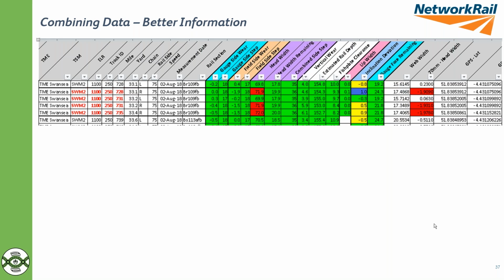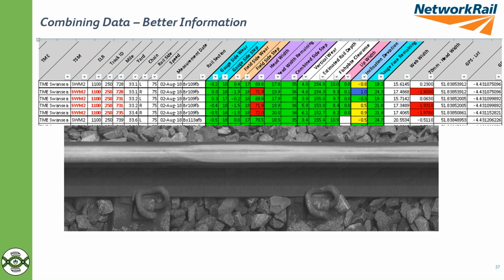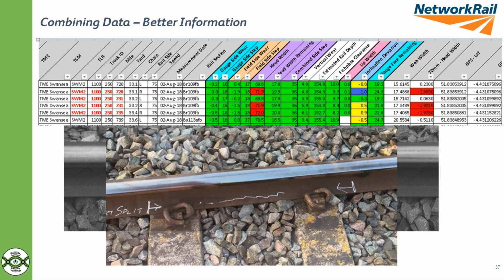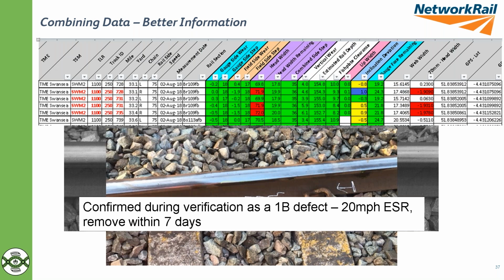It then got picked up by a UTU, and independently, a suspect was indicated from the UTU of a possible vertical longitudinal split. That is an image of it from the PLPR that we can see. You see the widening locally at that point. And when we got the ultrasonics out to confirm it, they were able to mark up the extent of it and measure the severity of it, and it was a 1B defect, that we then ended up removing. But certainly something like that, where perhaps the first telltale signs were around the head starting to spread, and then by the time we find it with our conventional ultrasonics, it can be quite late in the day. So ideally, we want to be finding these before we need to put a speed on, so we can plan their removal without affecting performance.